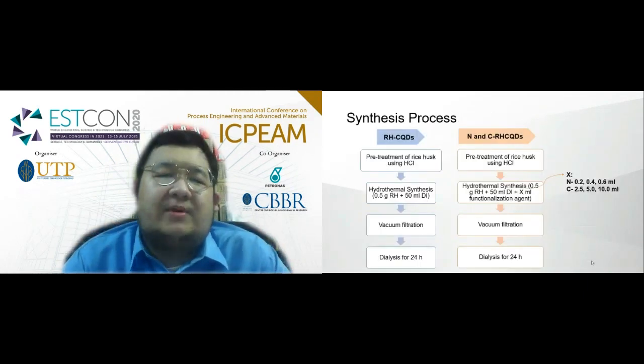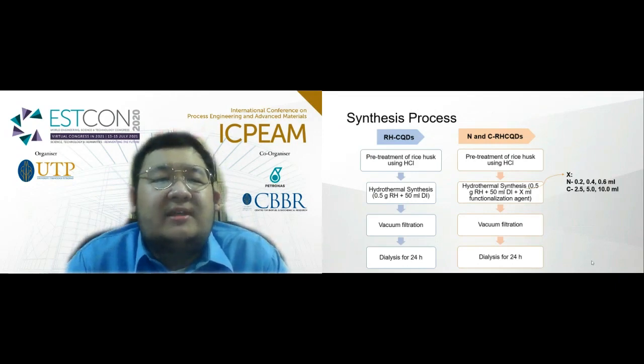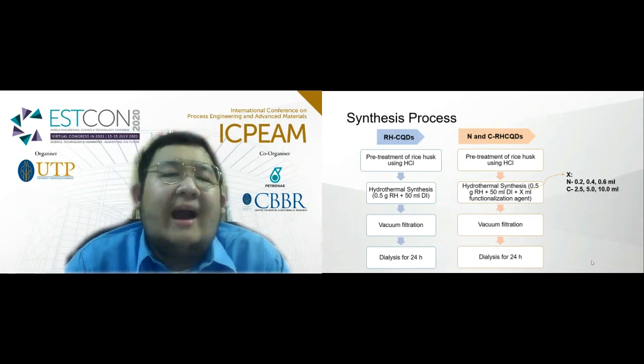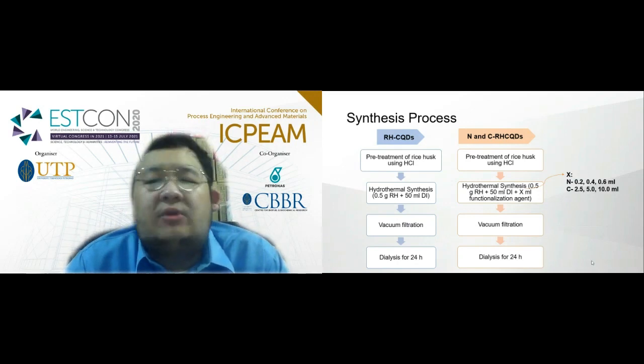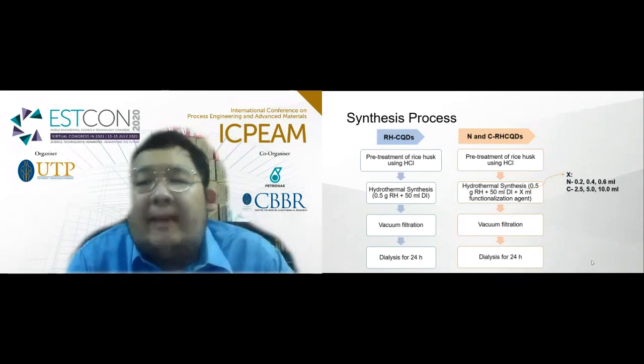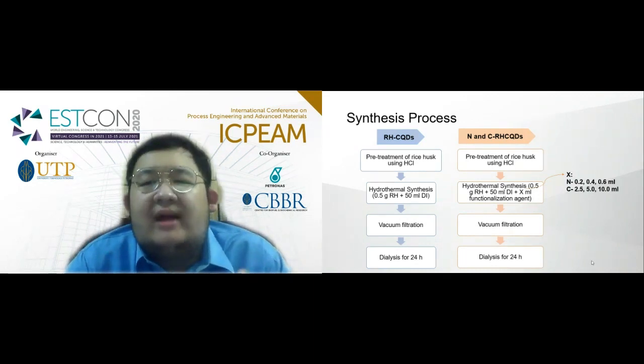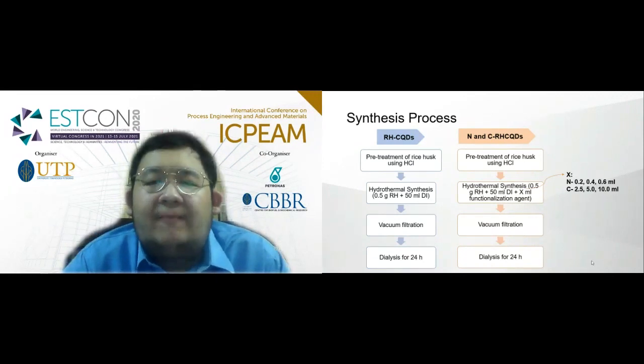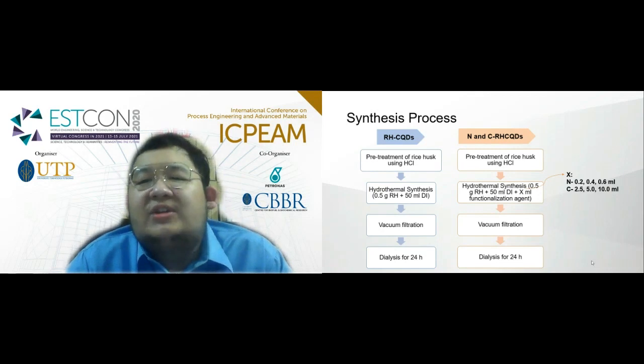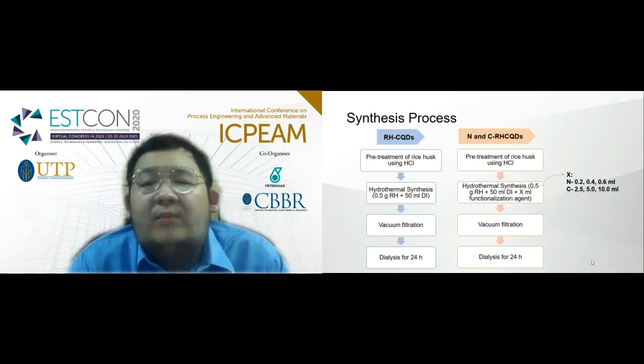Moving on to the synthesis process. We will start with the pre-treatment of rice husk using HCl, followed by hydrothermal synthesis, then vacuum filtration, and finally dialysis in order to purify the CQD. The functionalization will be varied, in which the EDA source, which is the amino functionalization agent, will be varied from 0.2 to 0.6 ml. The carboxyl functionalization agent, which is ascorbic acid, will be varied from 2.5 to 10 ml.